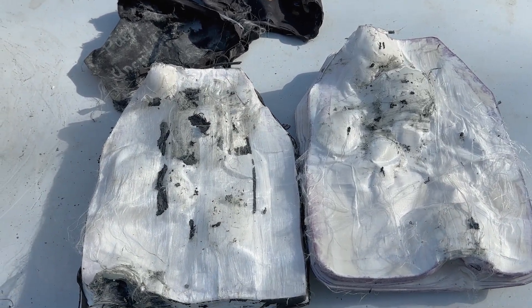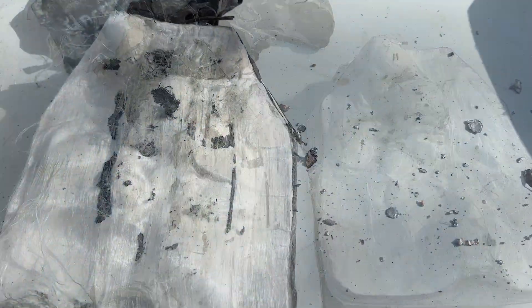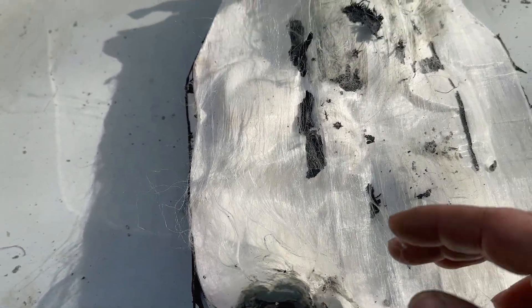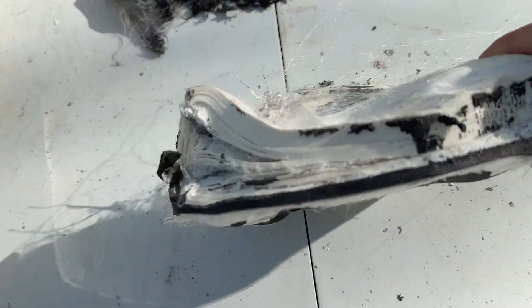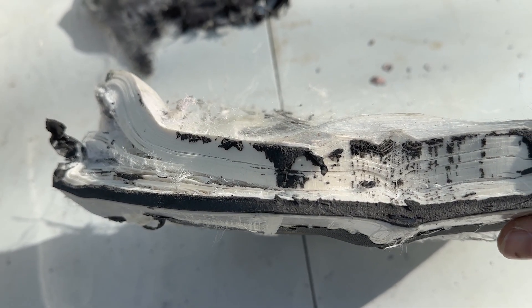But since this is 100% pure polyethylene, the measurements I take on the outside are pretty darn close, so you can make some assumptions there. For plate number one, the only pass-throughs — which weren't even true pass-throughs — were the edge shot of our mild steel core and the edge shot of M193. Otherwise, M855 up to the 22-inch was contained, as well as the stacked shot of M193. This appears to be pressed as well — it looks like it's pressed in layer sections and the sections are then put together, but it is still very rigid.